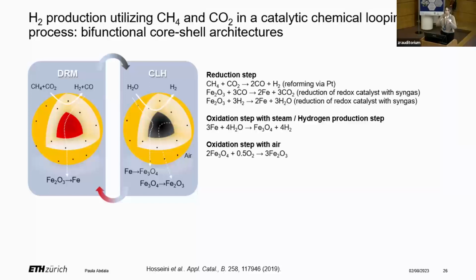And for this, we produce iron oxide nanoparticles that were covered with a shell of ceria. And there we deposited platinum nanoparticles on top, which will act as the catalyst. So the core is the oxygen carrier, and platinum on ceria is the catalyst.